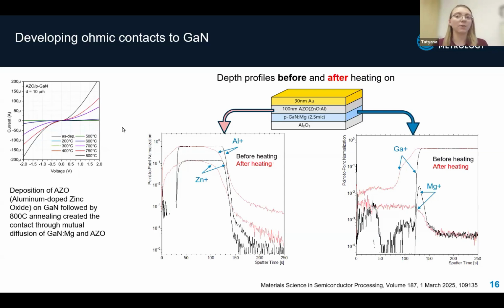This slide highlights how ToF-SIMS helps us analyze semiconductor contact formation, specifically between aluminum zinc oxide and gallium nitride. To give you some context, I would like to start from the sample description. 100 nanometers of aluminum zinc oxide, or as we call it, AZO, was deposited on a magnesium-doped gallium nitride layer with alumina as a substrate. Then a 30 nanometer gold layer was added on top to improve the conductivity. Now let's walk through the key findings.